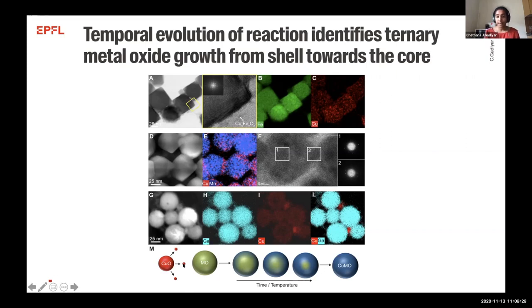From this, we concluded that the reaction mechanism is that first the copper starts diffusing and then it nucleates on the binary oxide. Then we have a shell of ternary oxide formed. And then at longer annealing times, the reaction front goes from the shell all the way to the core until we have a fully converted copper-based ternary oxide.